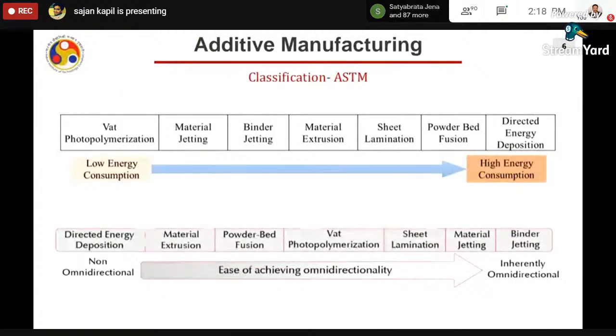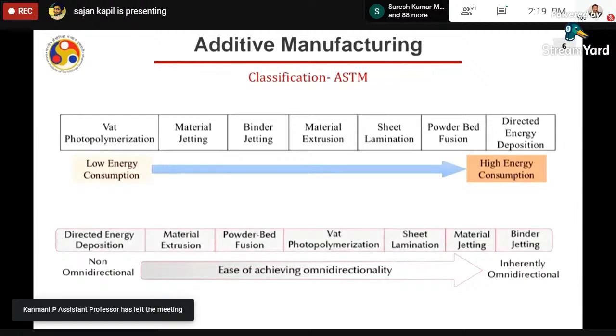So I am on slide number 6 right now. I'll just explain it a little bit again. So I was saying in ASTM they have classified from vat photopolymerization to directed energy deposition, and they lined up these processes in this way because vat photopolymerization utilizes the least amount of energy. Typically, the energy is in the range of 40 watt, while in the case of directed energy deposition, the energy consumed is in kilowatts, for example, 2 to 6 kilowatt. So it is based on low energy consumption to high energy consumption.